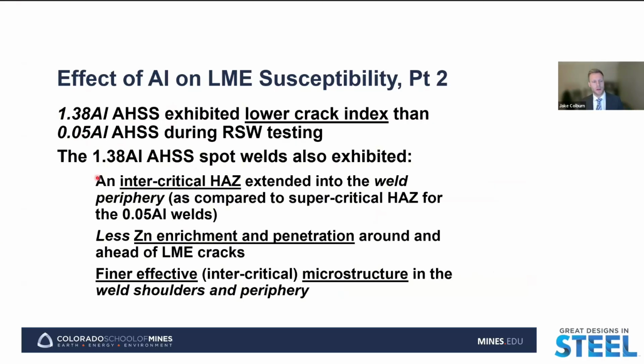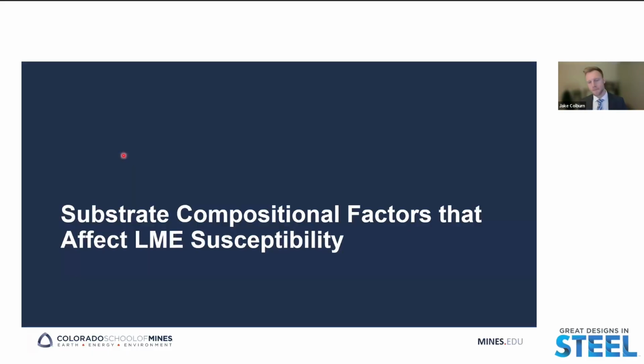And for this high aluminum alloy, we saw an intercritical HAZ in the weld periphery as compared to that supercritical HAZ for the low aluminum alloy. We saw less zinc enrichment and penetration for the high aluminum alloy, and a finer effective microstructure in the weld shoulder and periphery for the high aluminum alloy.